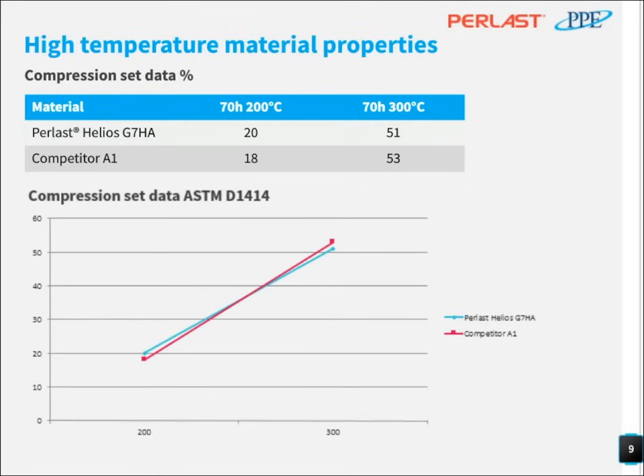So the compression set value of our material is 20% at 200 degrees Celsius and 51% at 300 Celsius. At the lower temperatures, our material is slightly worse than the competitor, but at higher temperatures, it's slightly better. So no significant difference. But at this point, I'd like to emphasize that the compression set test does not always give correct indication about the sealing performance.